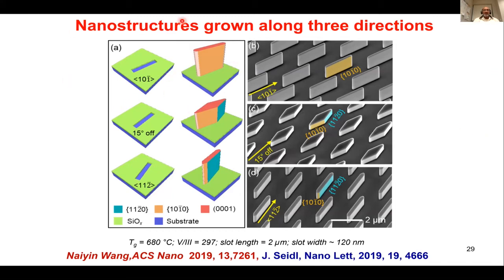Here is a case where Naiyin Wang opens a slot along a particular crystallographic orientation, puts it into the MOCVD reactor, heats it up, and introduces the gases needed for the growth of indium phosphide. You can create these beautiful membranes with these 5 side facets. But if you open the slot along another crystallographic orientation, this particular <11-2> direction, you again grow nice membranes, but they are thicker, and the facet you create is different because of the crystallographic orientation differences between this slot and this slot.